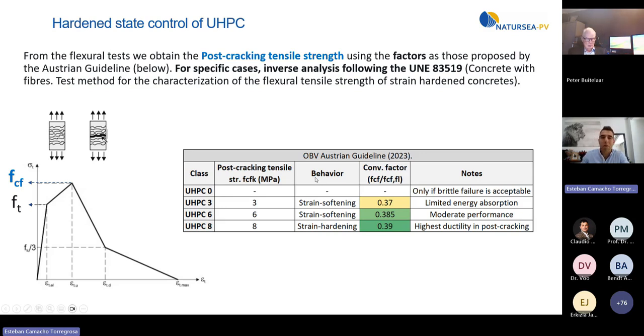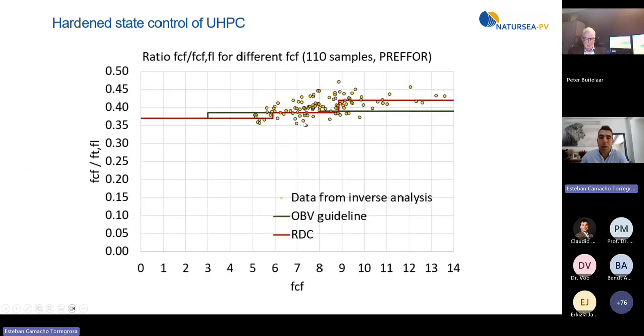Before applying this procedure with this simplified ratio, we made a lot of inverse analyses and obtained our own ratio. You can see this ratio in this figure. The yellow points are the ratio between the post-cracking tensile strength and the maximum flexural strength for our mixtures. And in blue or green, I don't know what this color is, you can see what the Austrian guideline proposes. So it's very similar, but not exactly the same.